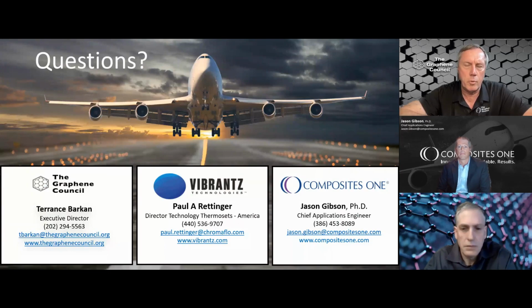Now, for the disposal of the material at end of life, the studies that we have seen, and there was just another recent one out, was that once graphene is incorporated into these parts, especially as a solid, it is virtually impossible unless you dissolve the matrix to liberate the individual graphene particles. In other words, if you took a composite material formed into a solid part and then sanded it, you are not going to liberate individual graphene flakes out of that plastic. It's too small. And then on the recycling side, because graphene improves the strength performance, if you had thermoplastics, for example, that you wanted to recycle, we actually have cases of using graphene to improve the recyclability of those materials, to improve their performance. So it actually enhances the recovery of those materials. And with that, I'll stop there.